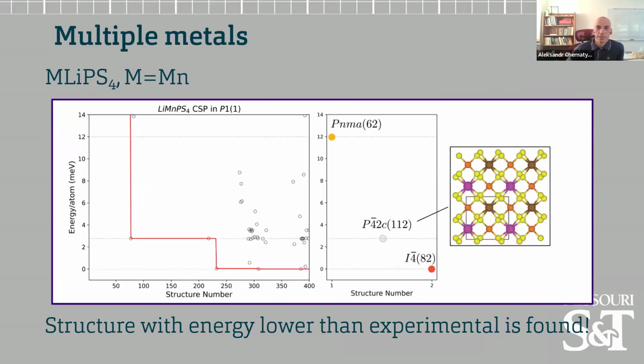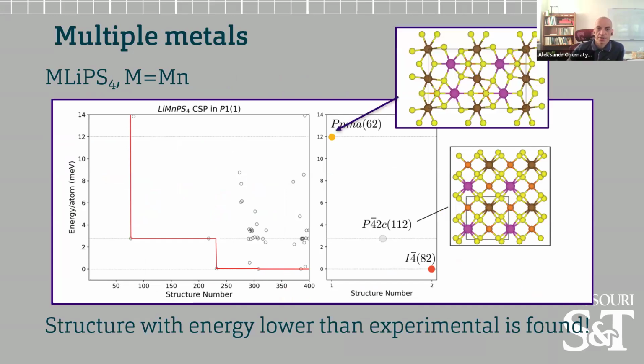In the case of manganese, life is a little bit more interesting. We found that the same type of structure as in the case of zinc is the lowest energy structure according to our calculation. Experiments, however, have found it crystallizing in group 62. And we, of course, can take the experimental data and calculate the energy of that structure. And we found that the energy of that structure is higher than the energy of our predicted structure.